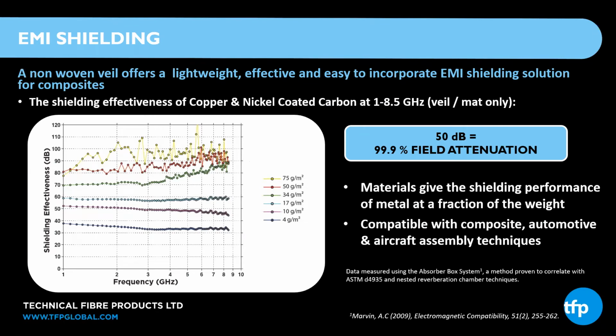On the x-axis, we have frequency in gigahertz. On the y-axis, we have shielding effectiveness in decibels. And this is looking at a copper and nickel coated carbon at 1 to 8.5 gigahertz. And we're looking at different areal weights. So if you look at the bottom line, you can see with 4 grams of very lightweight metal coated carbon, we're achieving about 30 to 40 dB of shielding effectiveness. As we move up through the areal weight through 10 to 17 grams, we're up at about 60 dB effective shielding, and then up to 34 grams, you can see we're into 70 up to 90 dB of effective shielding. So through selection of the particular fiber and the areal weight of the veil, we can achieve very high levels of tunable shielding performance. And at a very low weight in comparison to metal and in terms of application to the overall composite part.